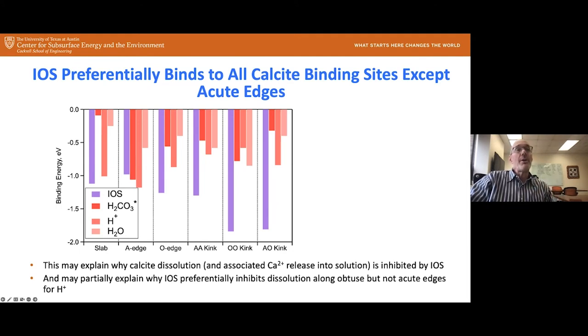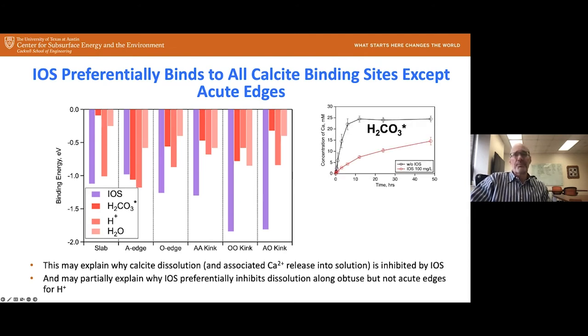All right. At the acute edge, it's a little bit different. Here we have the carbonic acid and the proton, which have a more favorable adsorption than the IOS, but the water has less favorable adsorption. Looking at these results, for carbonic acid, for example, we really slow down the dissolution with IOS, and that's what you would expect based on all these adsorption energies at these different sites where the IOS preferentially binds. Maybe not at the acute edge, but at the other sites for sure. So overall, it should slow it down.